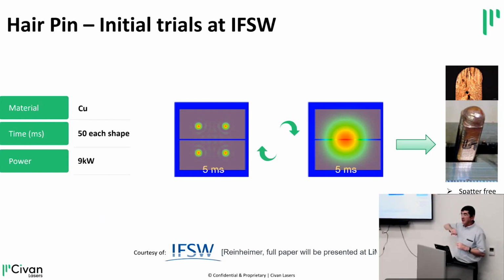to this bubble, okay? So everybody's working on doing things like that, but you have to do it without damaging the bottom. You have to do it when you have high tolerances between the different pins. You have to do it fast, and it has to have zero spatter and zero porosity. The spatter is because if you have spatter, it's going to make shorts in other places in the engine. If you have porosity, over time, this porosity with the shaking of the car is going to open up to cracks and break.